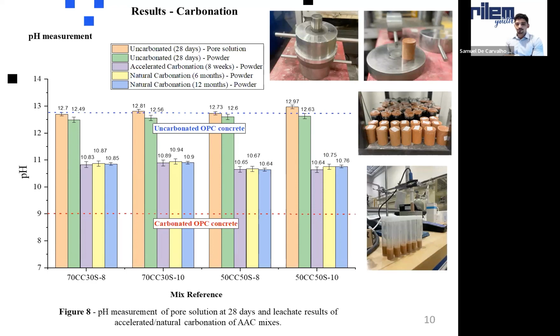So this particular pH measurement shows exactly the trend that not only our study was showing before, but also some recent studies in the past years show. It was showing that only a partial part of the composite was carbonated, which was only the pore solution. Most of the studies show that this particular pH doesn't pose any risk to the steel bar.